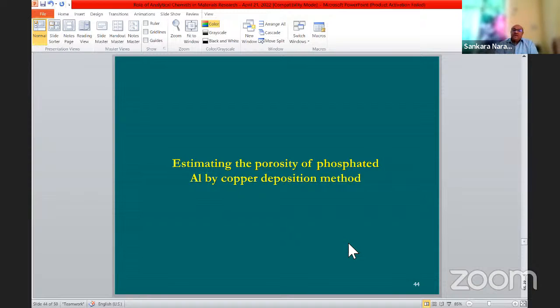The same thing you can do by deposition of copper. This is galvanic plating. Suppose we take a steel and immerse it in a copper sulfate solution. As per the electromotive series, the potentials are totally different, so immediately copper will get plated on the steel. The same thing, copper will be plated on aluminium. So we have developed a method to estimate the porosity of phosphate coated aluminium. Phosphate coating can also be applied on non-ferrous metals like aluminium and magnesium. If you apply it on aluminium, you can immerse it in a copper sulfate solution. So that's what we did.